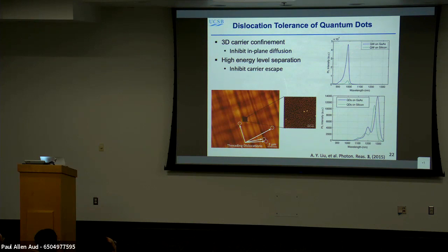That's a pretty standard result. In contrast with quantum dots, if you compare quantum dots in silicon, they're about the same. Now this image shows silicon being a little worse. I've got other images where it's exactly the same thing. We grow them side by side. There's no difference in PL from one to the other. So dots are really much brighter. They're much less sensitive to the dislocations. So again, here's this square right here contains all of these quantum dots, and there's the dislocation density right there. So there's literally thousands of dots per dislocation. And the carriers just don't diffuse far enough to see the dislocations. They get trapped in the local quantum dot.